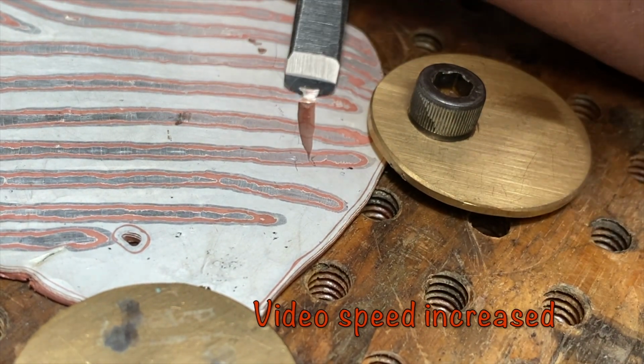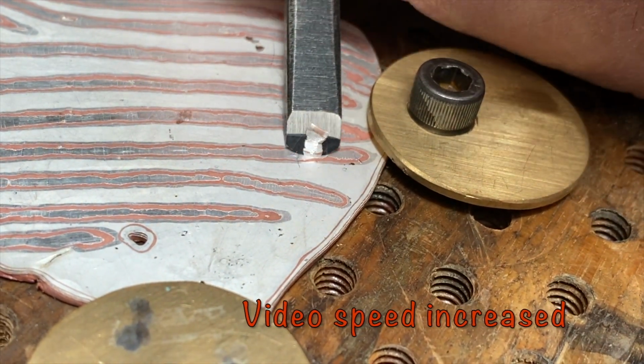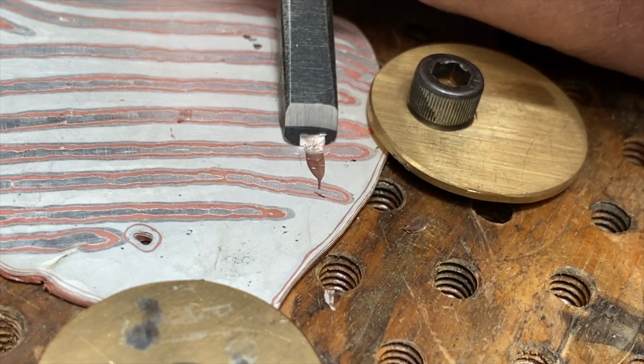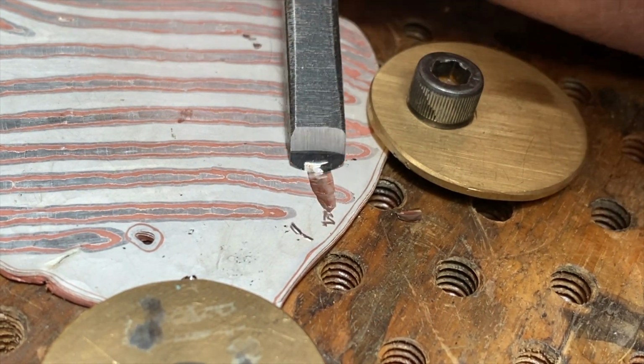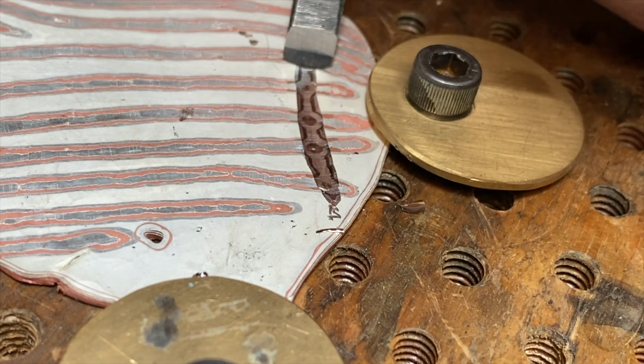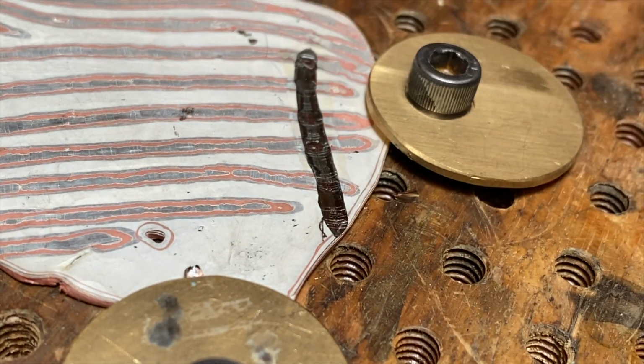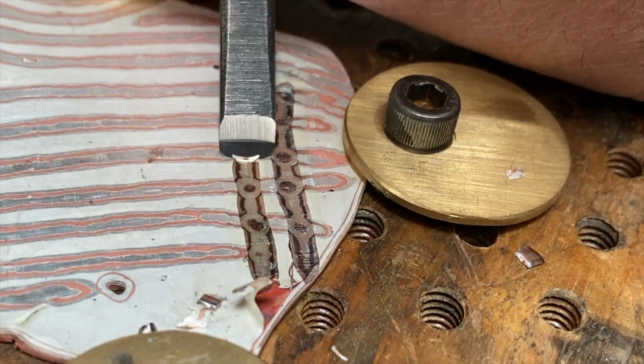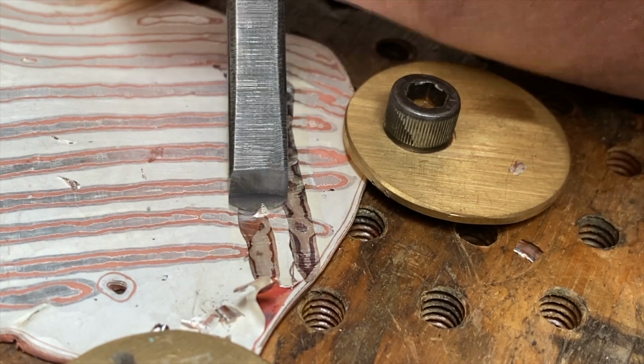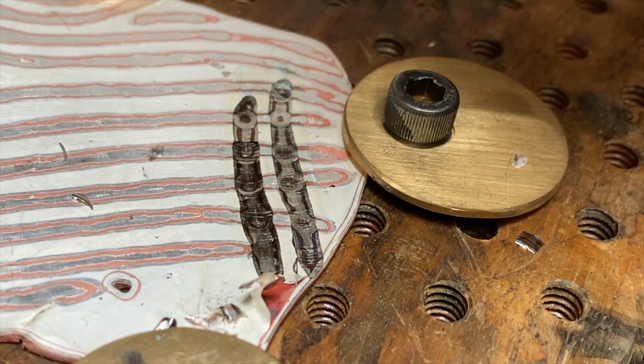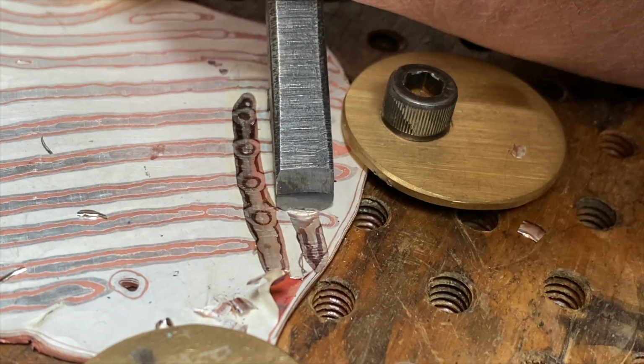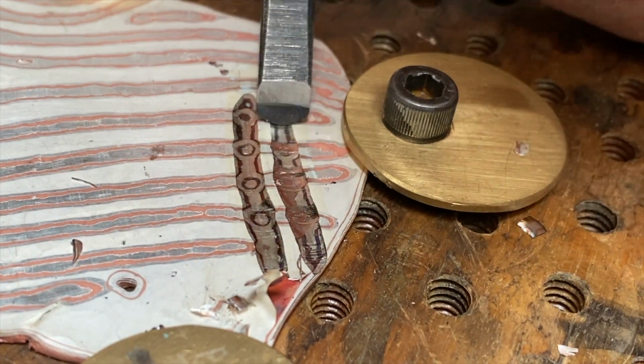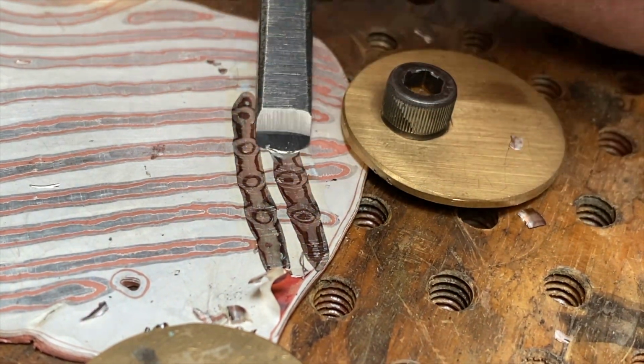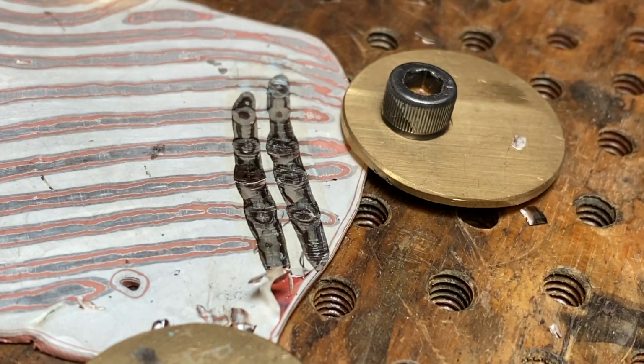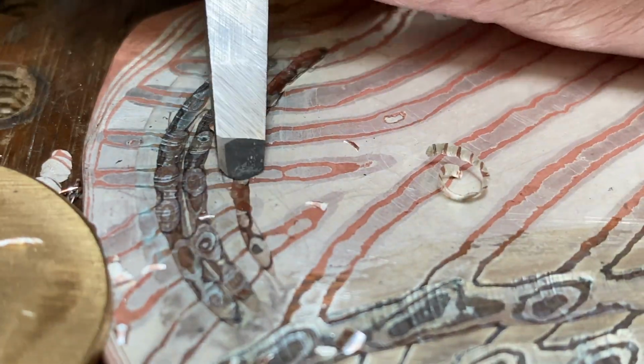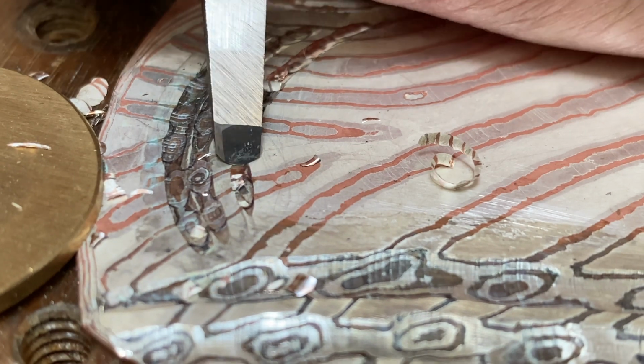Back on the patterning bench, I've begun cutting the crossing channels. You can see the new pattern emerging. In this demonstration, I'm keeping the bottom of those new channels at that third layer, and little spots like bullseyes happen where the lower layers have risen up to that third layer level where I cut across them. I'm refining the bullseyes, taking a peek at those lower layers. There's lots of interest here.